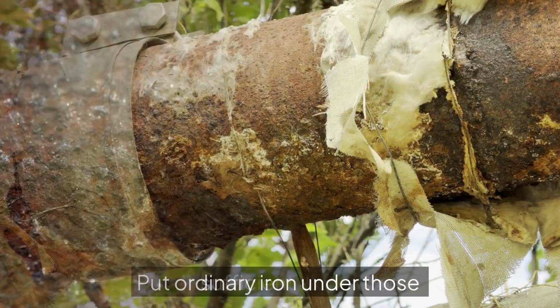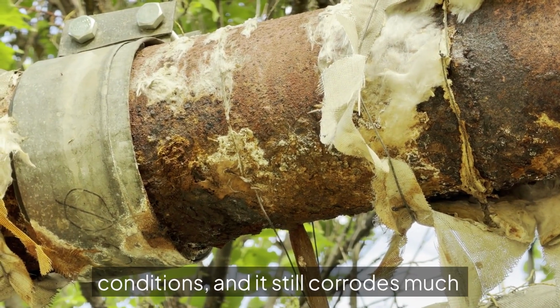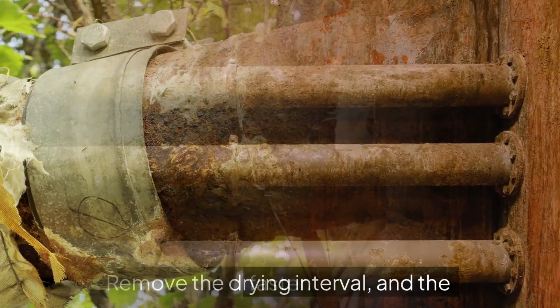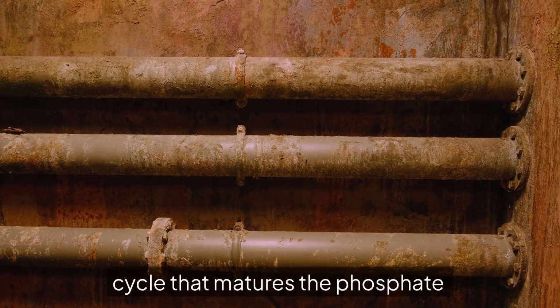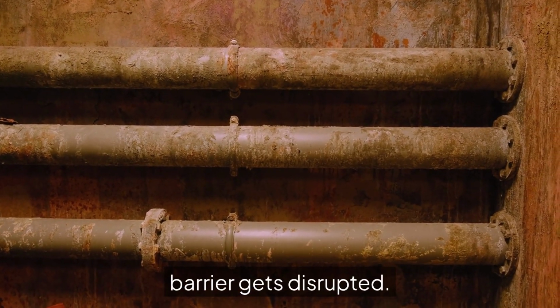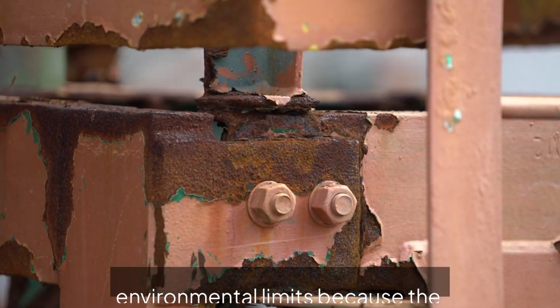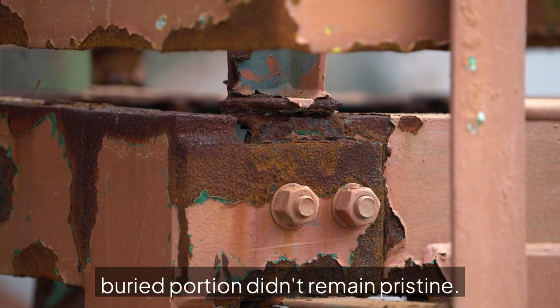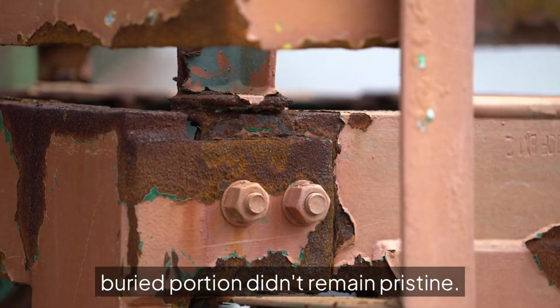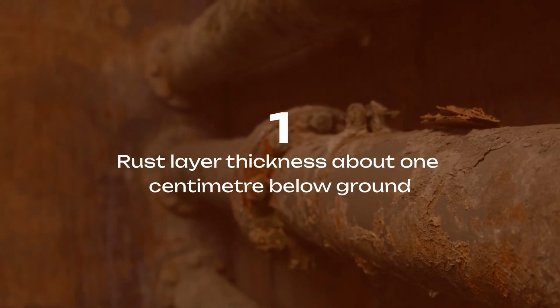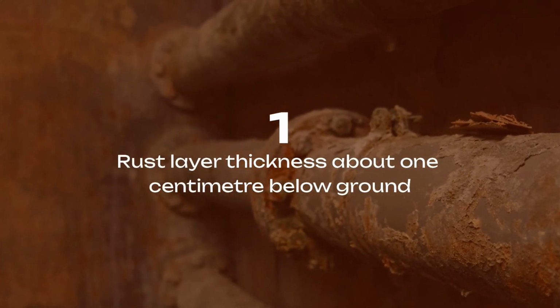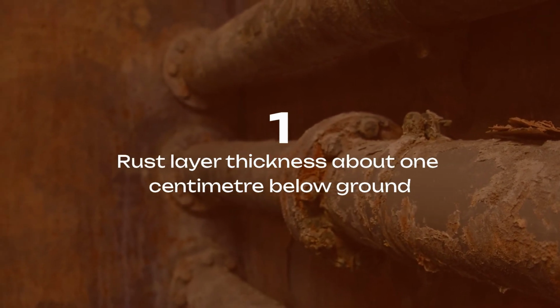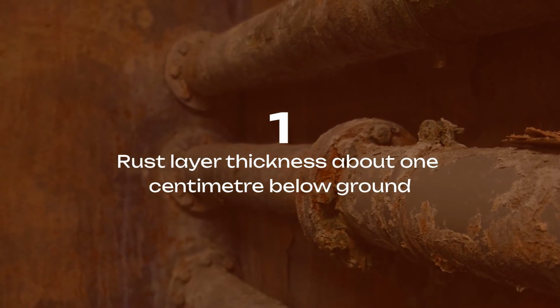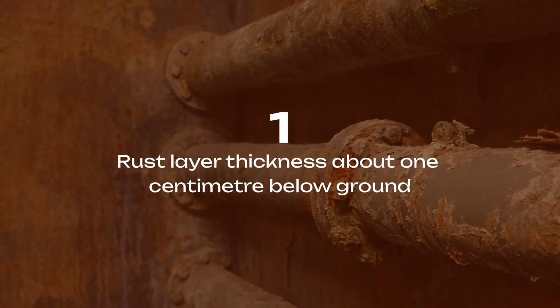Put ordinary iron under those conditions and it still corrodes much faster. Remove the drying interval and the cycle that matures the phosphate barrier gets disrupted. We know the protection has environmental limits because the buried portion didn't remain pristine. Researchers reported a rust layer about 1 centimeter thick and deep pitting below ground, while the exposed scale, by comparison, varies from tens to hundreds of micrometers thick.